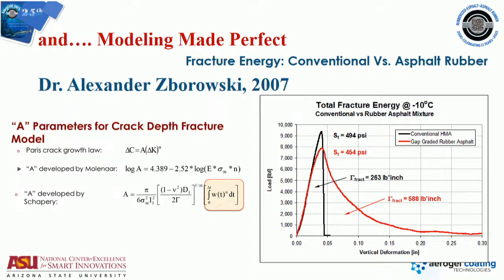They don't necessarily have the highest strength, but they have the highest post-peak residual strength, what you see in that red line above the peak, right? So the total fracture energy for these mixes is much higher, but that was not captured in any of the analysis that we have been doing back then, and maybe even nowadays. We were just discussing the other day, has it really made it to the new one or not? We don't know. And the simple math, I mean, Alex had to think about it for a long time. I remember he had to redesign the whole thermal fracture model in order to understand why and why not.